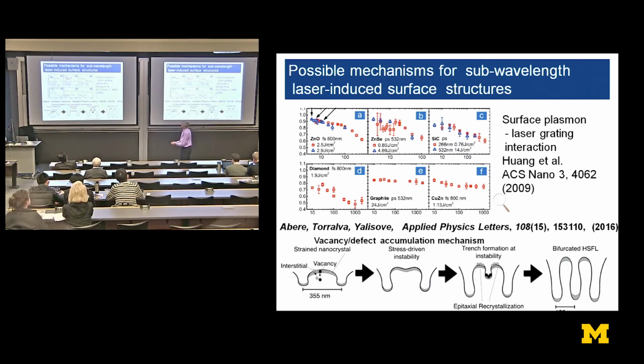between the valleys here. And after a given number of pulses, this can deepen where the vacancy and the strain is highest, and you can actually get a modification of the potential there due to the accumulation of many vacancies. And this can get deeper and deeper, and it can actually double the periodicity of the wire period as the number of pulses increases. So again, this is showing that there's a coupling between the optical field and the electron density of the material in a very interesting way.